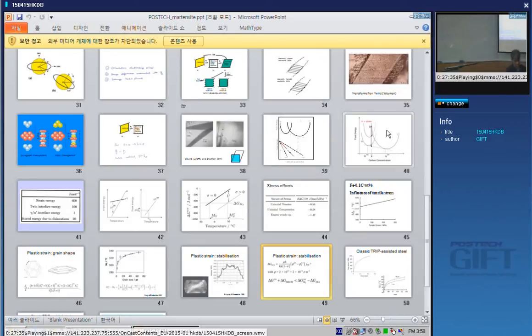Or you might get para-equilibrium, in which only the small atoms diffuse. But there's an infinite number of states between para-equilibrium and local equilibrium. There's no reason why it should follow equilibrium. So they are extremely difficult to model and predict. You have to make so many assumptions. With martensite, everything is solved. I'm exaggerating, but relative to other transformations, everything is solved.